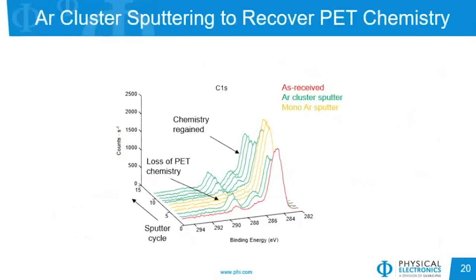Another example of showing polymer cleaning with the argon gas cluster is here on PET. The as received spectrum is shown in red and has adventitious contamination on it. As we sputter it with argon cluster, we can see that we develop the spectral shape representative of PET. Then if we try sputtering it with a little bit of monoatomic argon, the peaks at 286 and 289 disappear, and we get a higher peak around 285, which is representative of just carbon-carbon bonding. We can actually continue with our argon gas cluster sputtering and eventually remove that damaged layer of material and preserve our original PET spectrum.